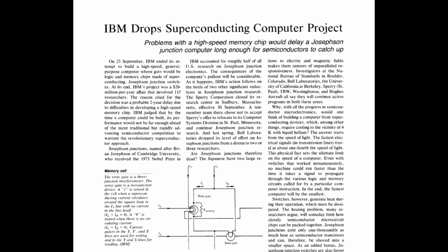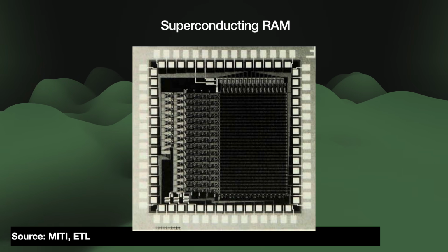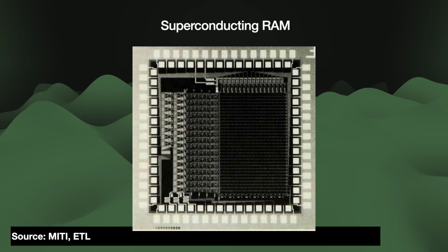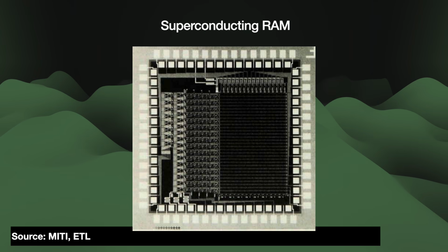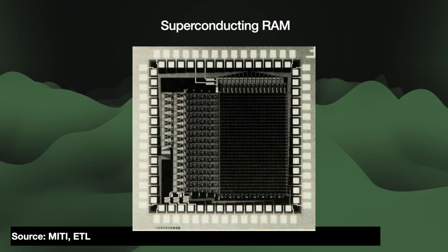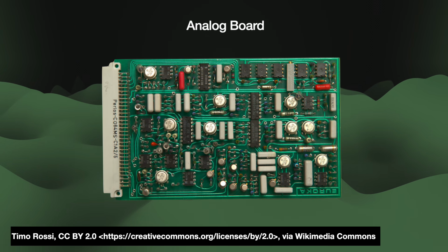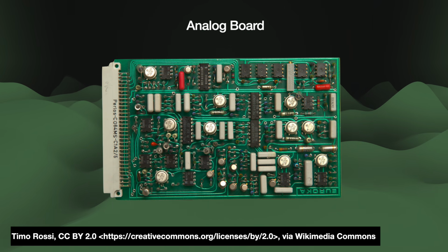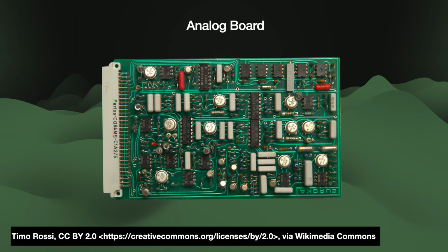The largest Josephson-only memory unit ever produced was a 4 kilobit unit produced in 1990 by NEC. The reason the memory issue exists is that it is extremely difficult to produce these junctions in large densities. Similarly, this is why the most successful Josephson-based systems have been analog systems and the like. Analog systems handle real-world signals like power or sound. They have only a few components, so it's easier for superconductor-based integrated circuits to compete with them.